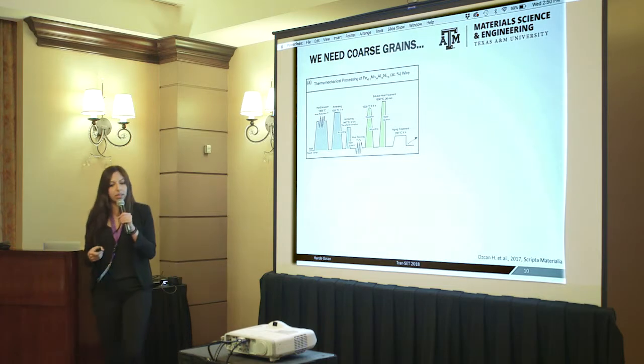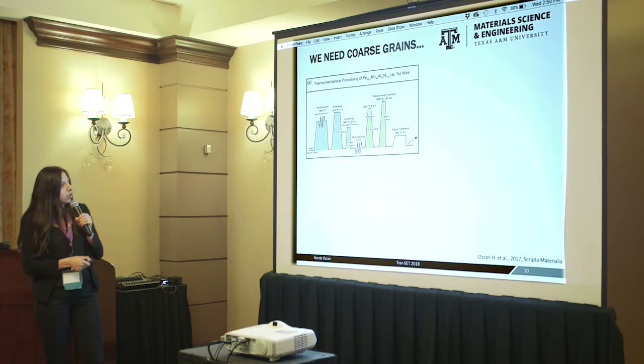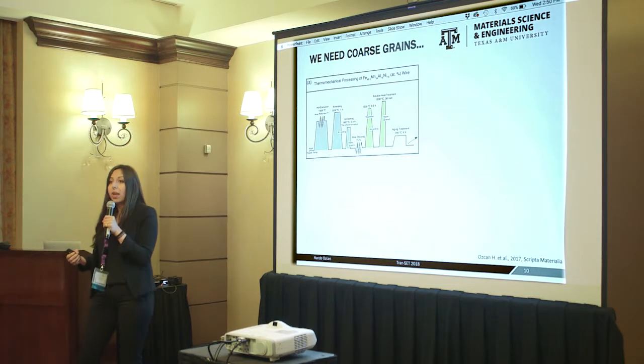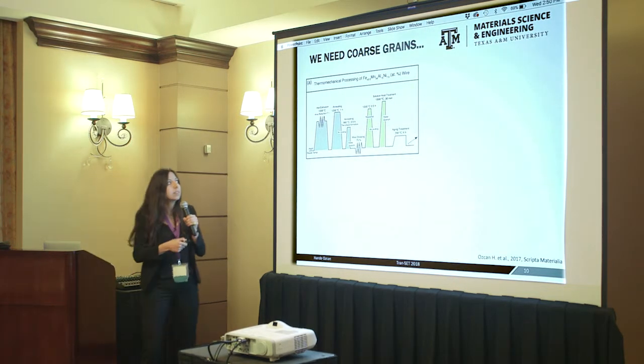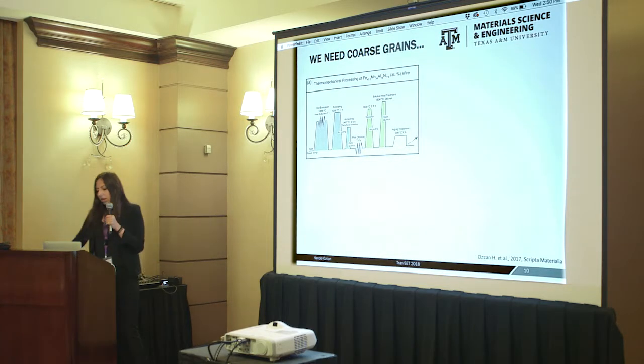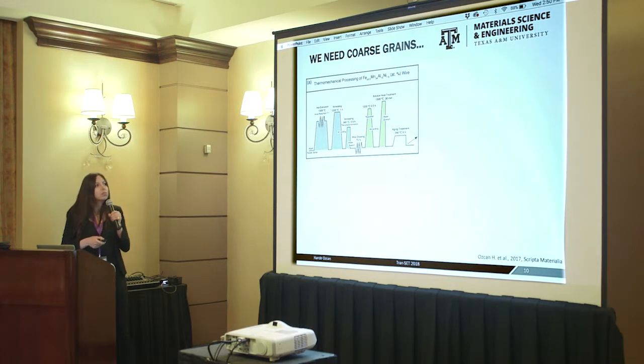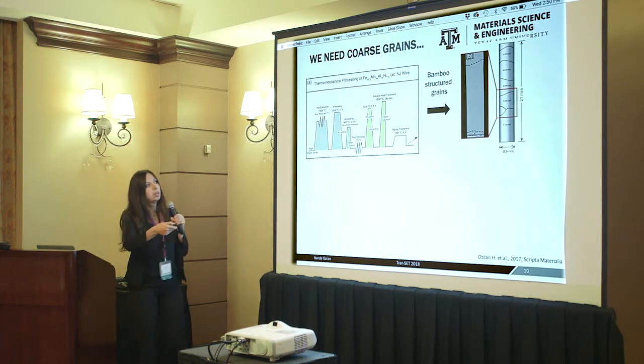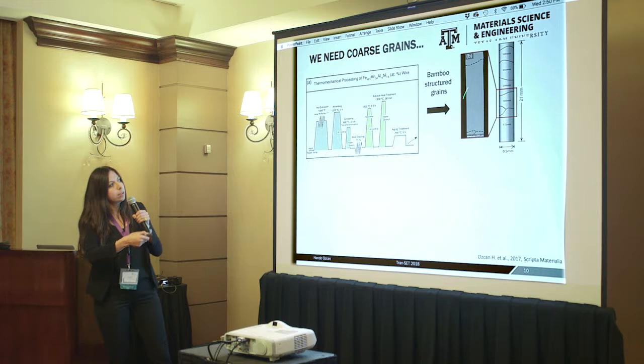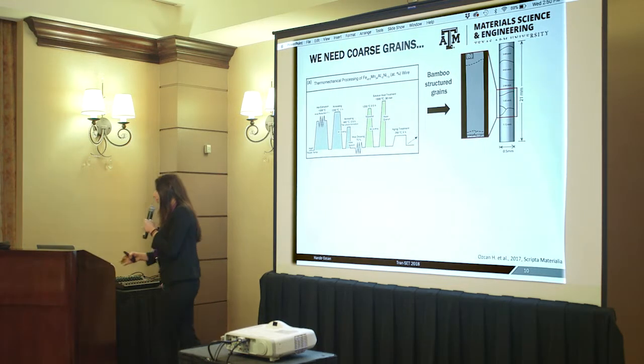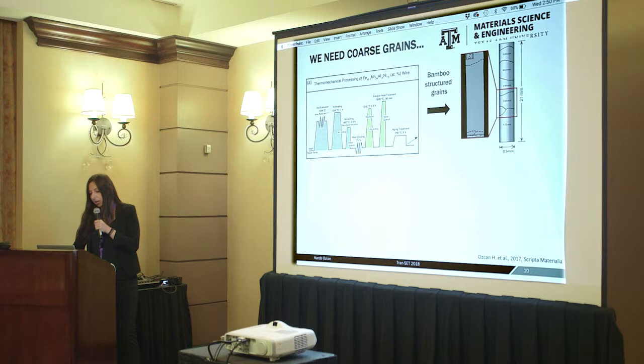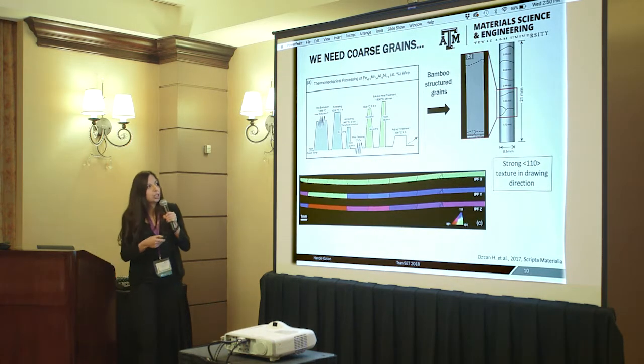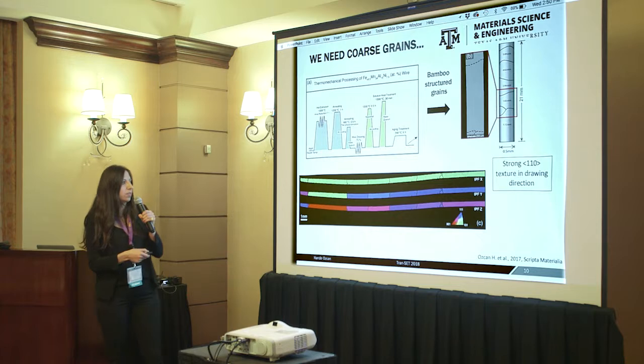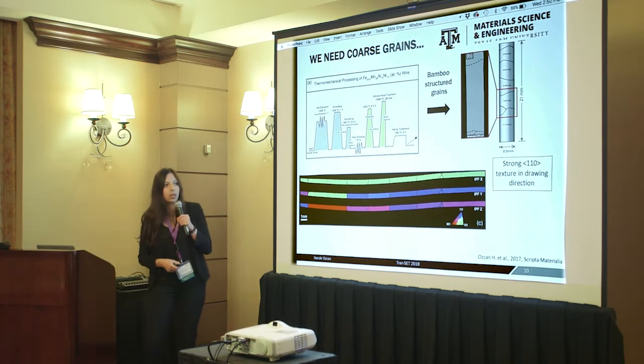Of course, in our group we've done lots of studies to find ways to increase the grain size. This looks complicated, but you can divide it into 2 processes, and it's more simple. We did this thermomechanical processing beforehand, and I'm not going to go into details, but after that you can get these huge grains, which I'm currently studying right now. After you apply these processes, you get very big grains with a very strong texture in the 110 direction.